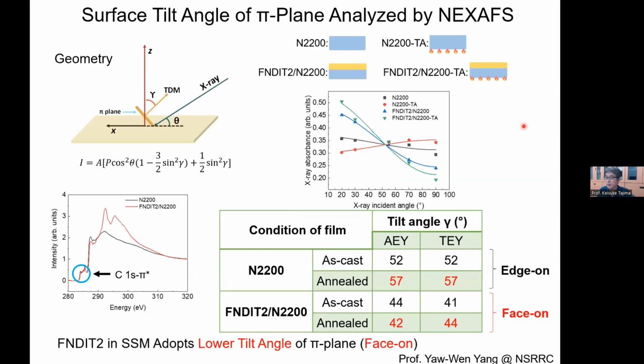What about the molecular orientation? Well, it's really tough to analyze the molecular orientation on the surface. But one good way is NEXAFS, maybe you know, this X-ray absorption technique. This is collaboration work with Professor Yang at the Taiwan synchrotron facility. I won't talk about the details of the measurement, but the important point is that we use the carbon 1s pi-star transition of this X-ray absorption, and this transition dipole moment is known to have a direction normal to the pi plane. So if you know this, by changing the incident angle of the X-ray, you can tell the angle of the pi plane from the surface normal of the film.